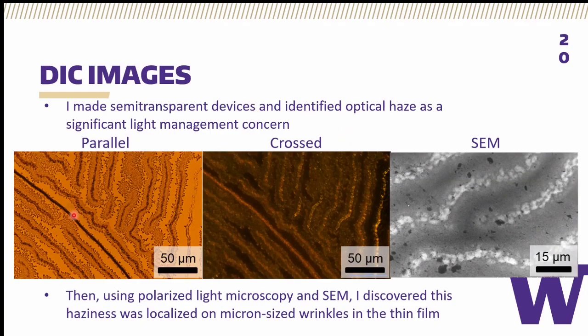It has a negative correlation with the intensity of the parallel polarized case. And we see that this haze that we're observing in our UV-vis spectrum is localized on these surface ridges, which others have characterized in the literature as a wrinkling of the thin film. Which is particularly problematic with these wide bandgap materials, which is why we, working with these bromide materials, have had problems with this, whereas people working with the iodide-based material systems have not had quite as many problems. And using SEM, we were able to see that these ridges are present there as well and are clear topography of the film and not some sort of local dielectric change.